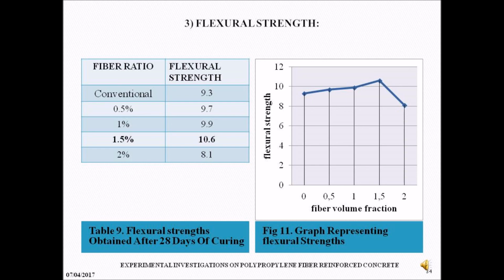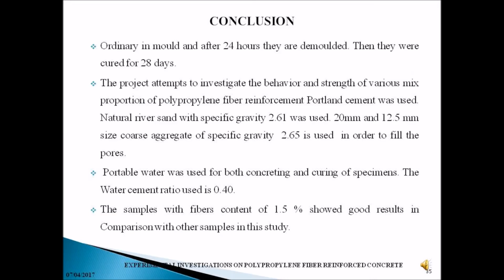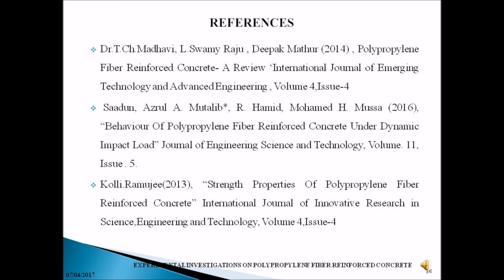as shown in the graph. Well, coming to conclusion, specimens are cast and after 24 hours they are demolded and cured for 28 days. Potable water is used for concreting and curing of specimens. Water cement ratio 0.40. The samples with fiber content of 1.5% showed maximum results, and these are the references we used here.